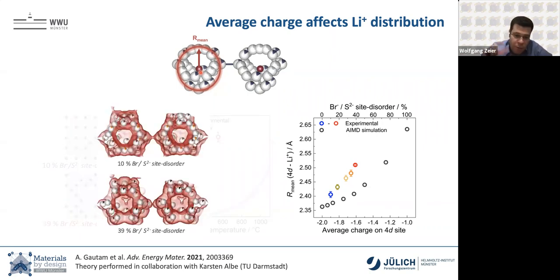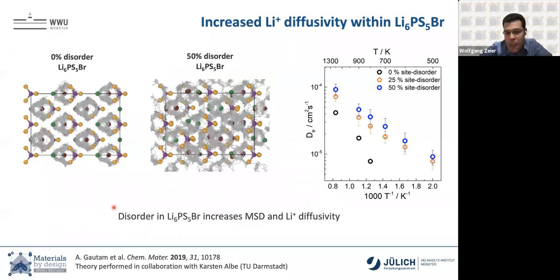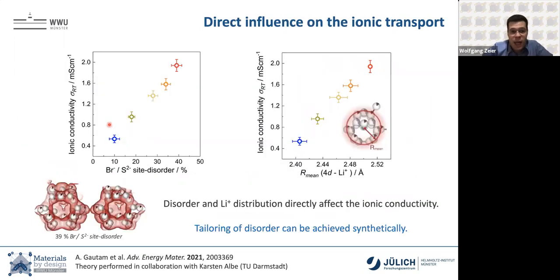And when you take neutron diffraction data and you calculate the isosurfaces of where lithium can be found via the so-called maximum entropy method, you actually see that the cages at low disorder are much more constricted, and the cages at high disorder are much more spread out. So there's really a much better connectivity the more disorder there is. And our collaborators from Darmstadt actually looked at that in MD, and you really see that if you use a material that has no disorder, these ions just rotate fast around the cages, but there's no jumps happening. As soon as you turn on this disorder, lithium moves throughout the whole unit cell, and these materials become amazingly fast ionic conductors. And so we can plot in the study of quenching from different temperatures the ionic conductivity versus the site disorder, and it scales directly with the site disorder, or it scales directly with this R mean. So really, by tailoring synthetically this disorder, we can directly affect the ionic conductivity.